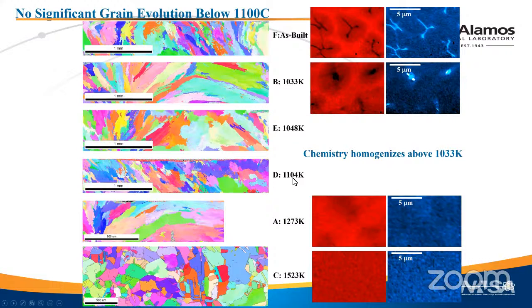that chemical heterogeneity that I told you, that drops out between, well, 1000 K and 1100 K. You see it starts out with the areas of chromium, reduces a little bit in the lowest temperature sample, and these are rather time consuming, so we didn't get to do it for every sample. But you can see now up about 1200 K, that chemical segregation has gone away.